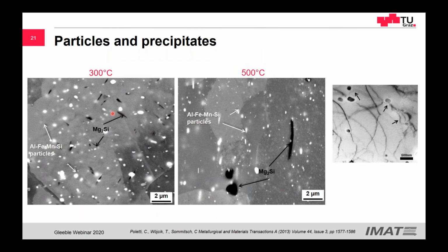So we also saw that particles like Mg2Si can have an influence on the dislocation movement, as you can see here. So the interaction of dislocations with particles. And by increasing the temperature, we make the material soften, usually because we increase the movement of dislocations. But additionally, in this case, since we lose or dissolve these black particles here, we also allow dislocations to move even easier, and therefore the material gets even softer at this temperature.